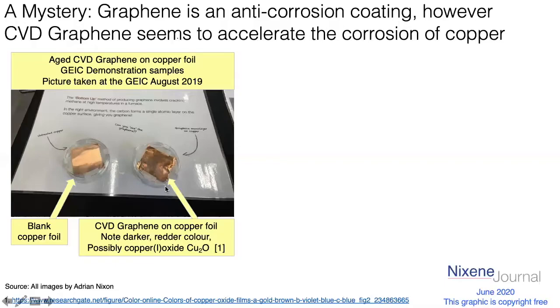So we can see here that the darker copper foil sheet has gone darker and redder, and that's due to what looks like copper oxide that's formed under the surface. This oxide means that some corrosion has been happening on the copper. Yet everybody knows that graphene is supposed to protect copper from corrosion. And now what we're seeing is that the graphene coating seems to accelerate the corrosion of copper. These two foil samples were made around the same time, and the graphene was coated onto one sample, while the other was kept bare. So they're the same age, and yet the copper with the graphene on was corroded more than the one without. That seems to indicate that the graphene is helping the copper corrode, which is exactly the opposite of what we expect. So it's a bit of a mystery, isn't it?